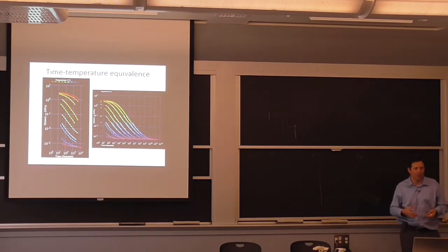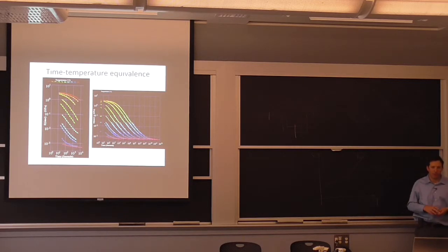It's not something that you can do in just a couple of days, because you don't want to accelerate it to a point. This is huge acceleration. You're extrapolating over 6 orders of magnitude. It's not something that you can be sure that it's going to be the same mechanism of cracking.